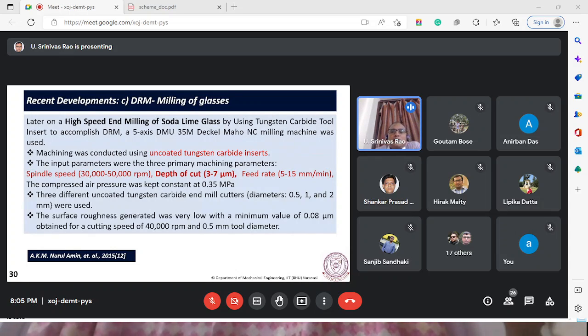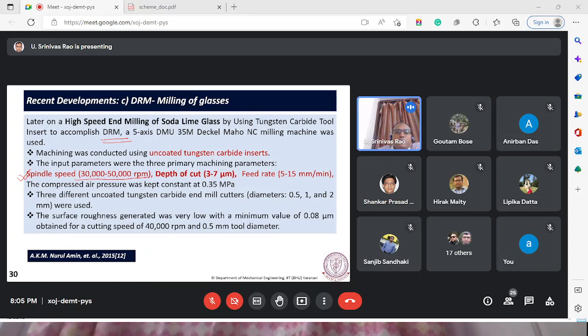In this you can see the high speed end milling of soda lime glass using tungsten carbide tool inserts to accomplish ductile regime machining. The tool used is an uncoated tungsten carbide insert, and the spindle speed is 30,000 to 50,000 rpm. What is critical is that the depth of cut is 3 to 7 micrometer. It's a very small value. If the machine is not very precise, half the time it will not touch the surface. So this level of values is required for ductile regime machining.